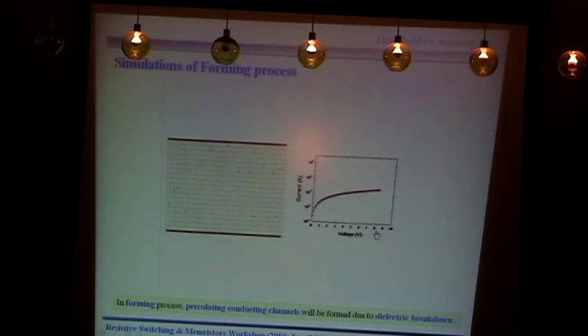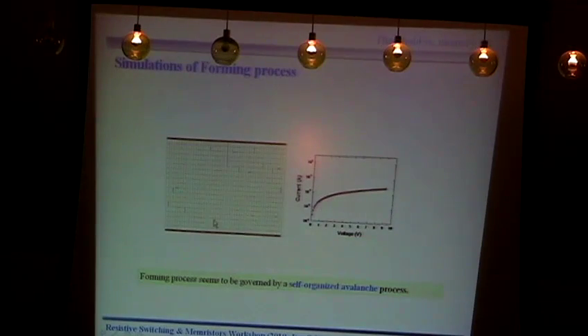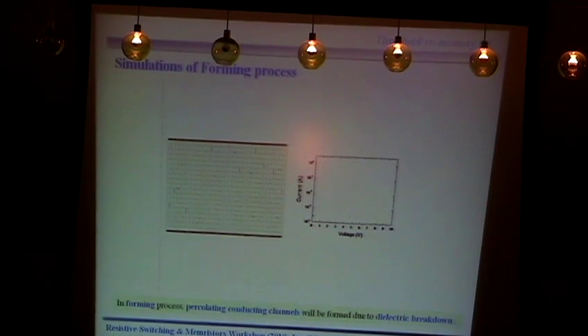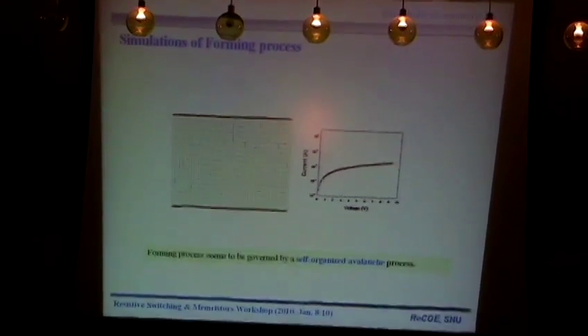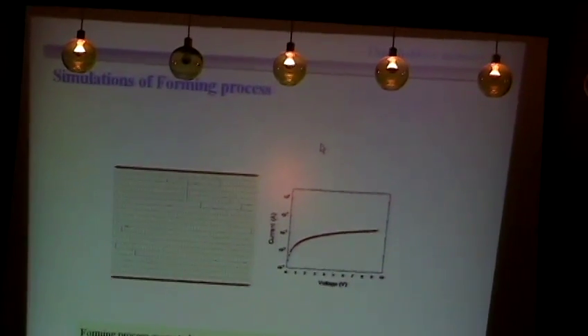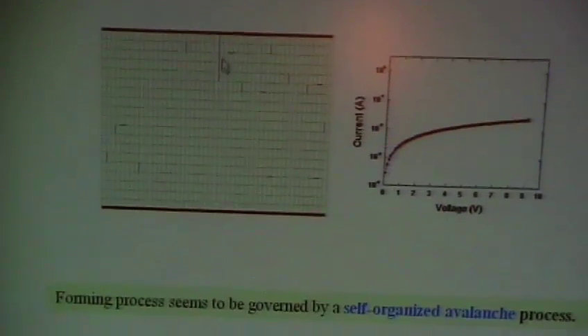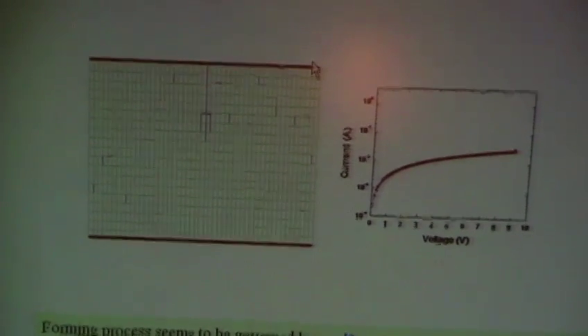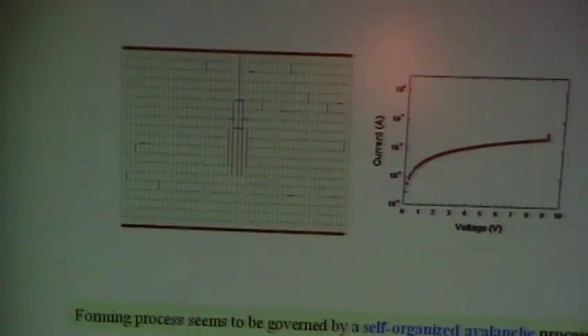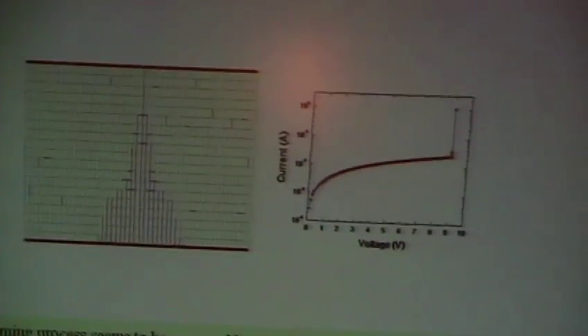However, when you reach around 8 or 9 volts, you can start to see that you do have a percolation channel developed across the sample. So if you look at the percolation channel, it approaches certain voltages. Then, at high enough voltages, you can see that some of the circuit breakers in this region will satisfy the switching rule. After they are switched, some more circuit breakers around this region will satisfy the switching rule. So it just propagates.